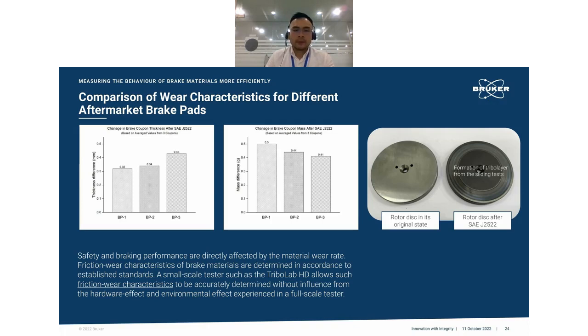So the friction and wear characteristics of brake materials in this test, we are determining in accordance to established standards. We measure the thickness difference and also the mass before and after the SAE J2522 test. A small scale tester such as the TriboLab HD allows such friction wear characteristics to be accurately determined without influence from the hardware effect and environmental effect experienced in a full scale tester. This type of approach will be exceptionally helpful for those manufacturing or developing brake pads, to evaluate how effective the braking performance of the particular brake pads is.